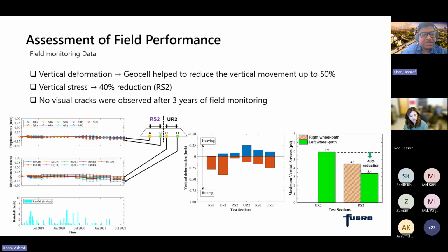So let's look at the field assessment results. When we check the results from the field, we observe that typically Geocell reduces the vertical movement up to 50%. So, the comparison between the reinforced and the unreinforced section. And the vertical stress on the reinforced section was like 40% less due to the use of Geocell.